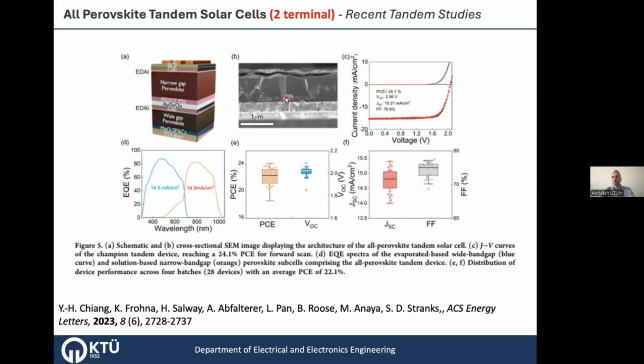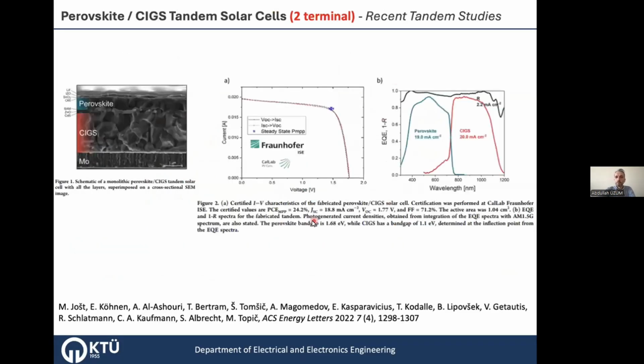Here is an SEM image of it, and an efficiency of 24.1% is achieved. And you can see the drivers of efficiency, JSC, FF, and other parameters of the solar cell. Again, as I said, the bottom and top cell can be changed. This is another example, using a CIGS solar cell as a substitution for the silicon solar cell. It has a band gap of 1.1, and the perovskite top cell is around 1.68. So it's a good monolithic tandem. These are all monolithic tandem solar cells.